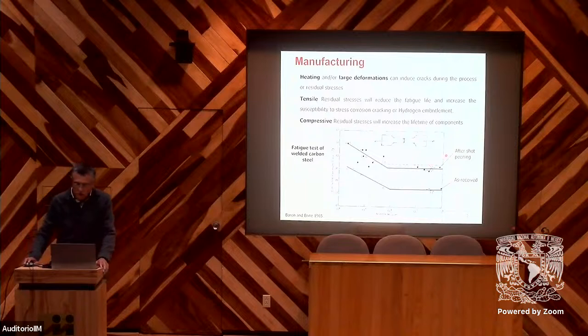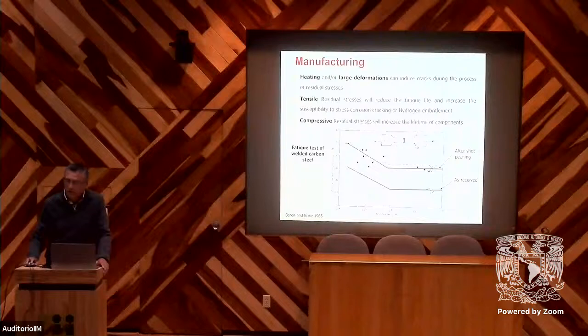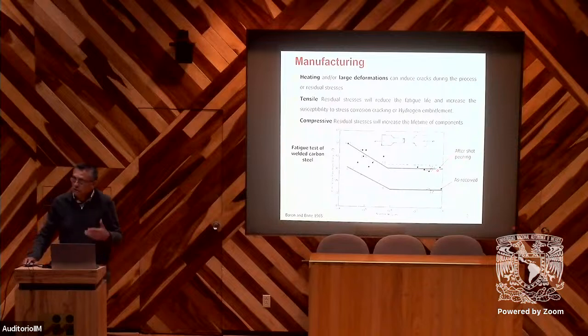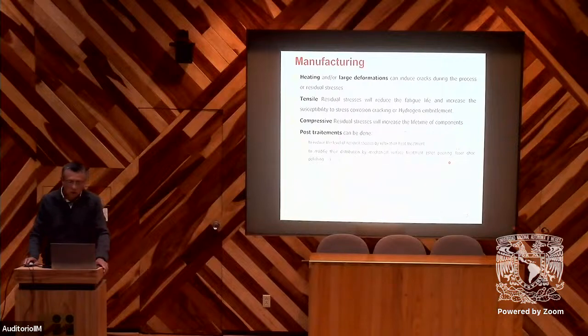These are very old results where we compare as-received material after welding and a specimen after shot peening. We can see that shot peening induces compressive residual stresses at the surface, so this improves the fatigue life of components. We can see here the as-received material, this is the Wöhler curve, and this is the improvement after shot peening.